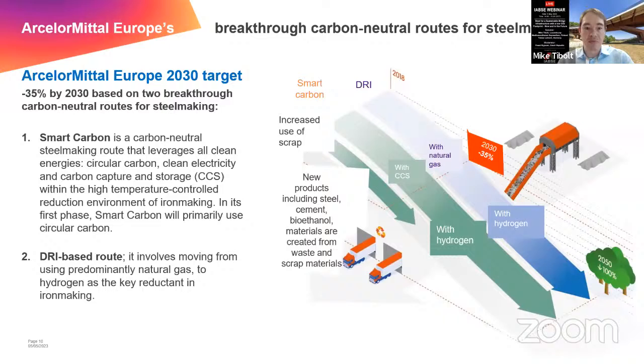The same is true for the second breakthrough technology, the DRI-based route. In the first step, until 2030, this route will be mainly based on using natural gas as a reductant element, but in the long term, it is foreseen to replace it with hydrogen. And then we have a third one, which will only be applied in the short term. It is to increase the use of scrap in the blast furnace route, to also reduce the CO2 emissions in the blast furnace by increasing the scrap content.